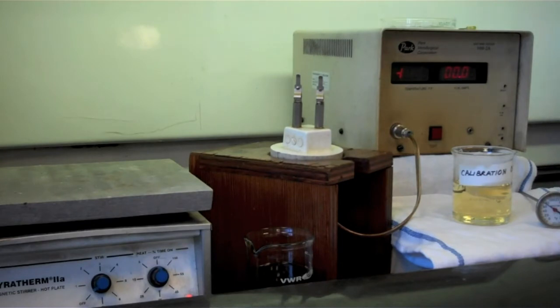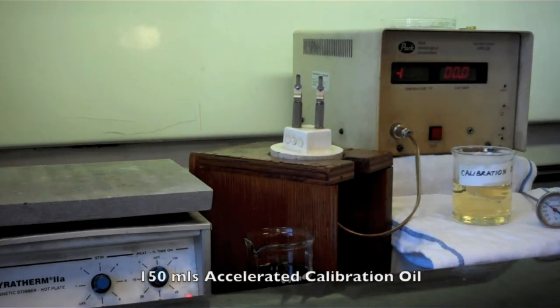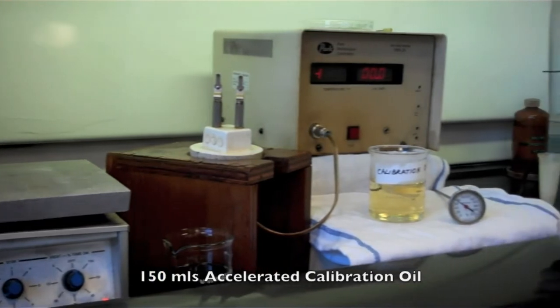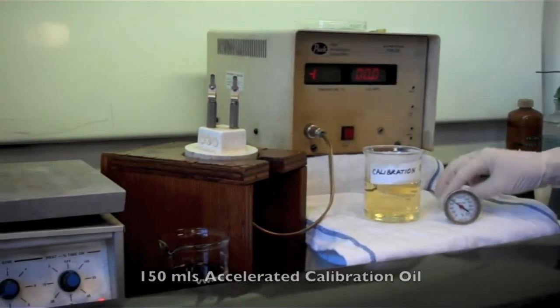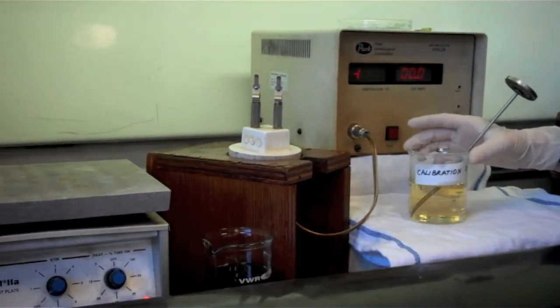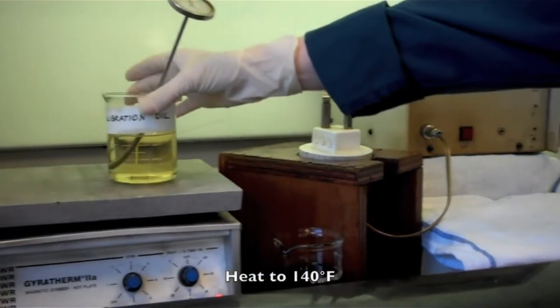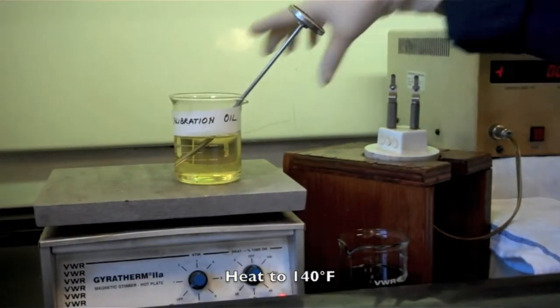Before testing an oil sample, we need to calibrate the apparatus. We are going to use an accelerated calibration oil as a reference. How do we do it? We pour 150 ml of the accelerated calibration oil in a beaker and heat it up on the hot plate to 140 degrees Fahrenheit.